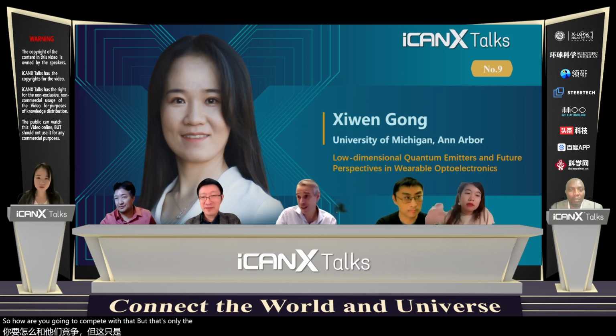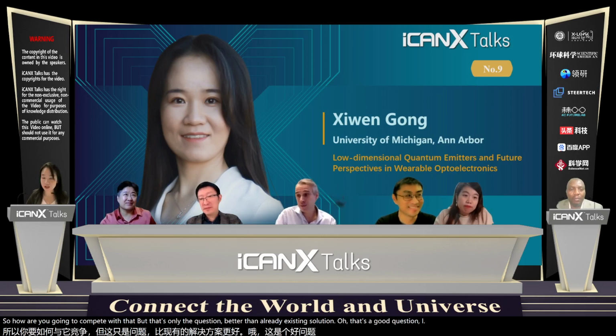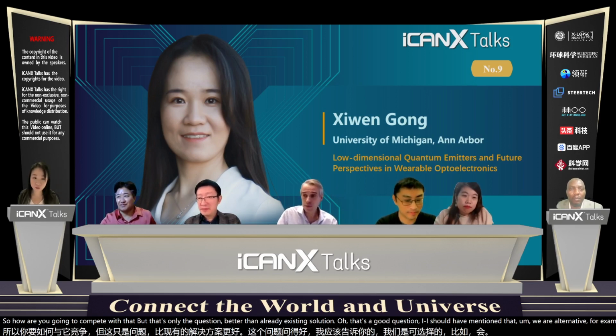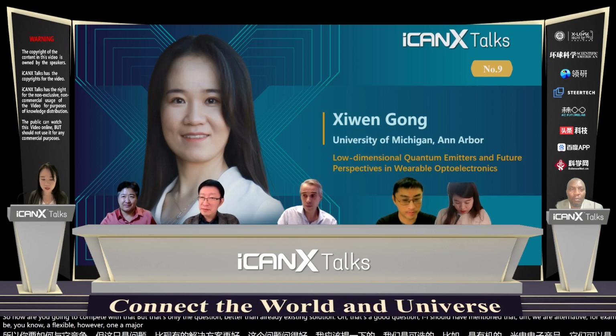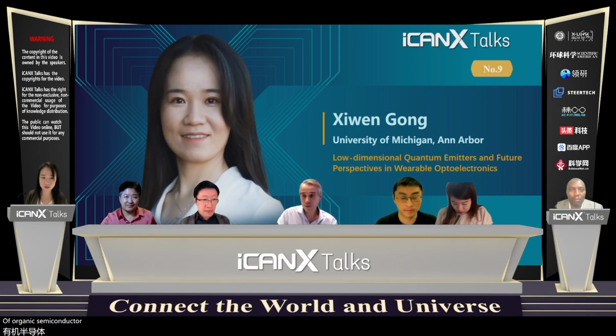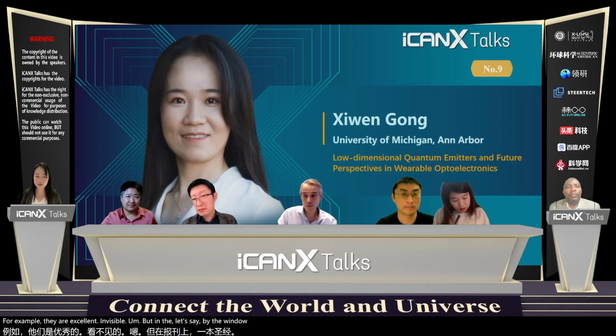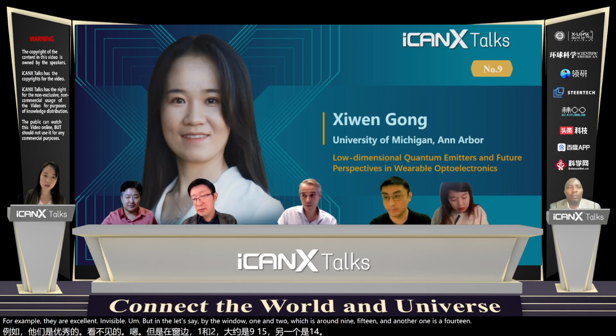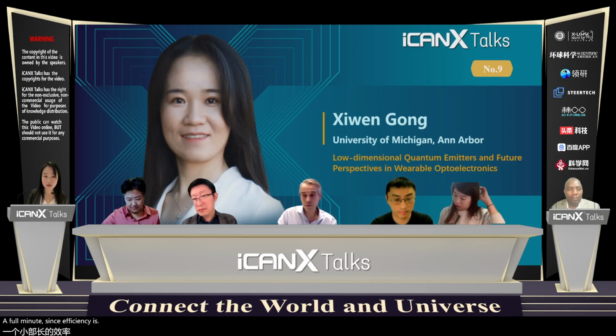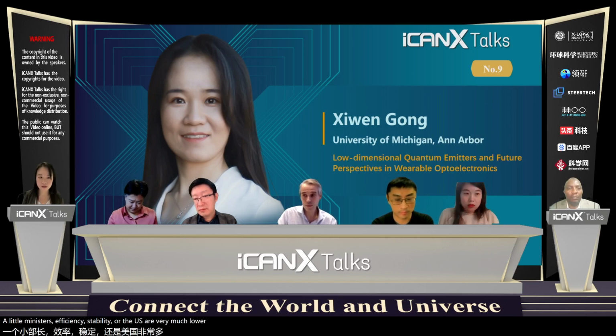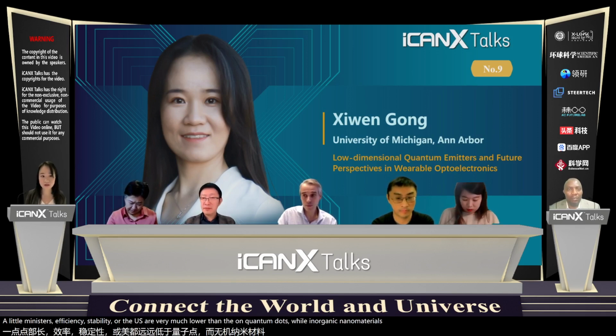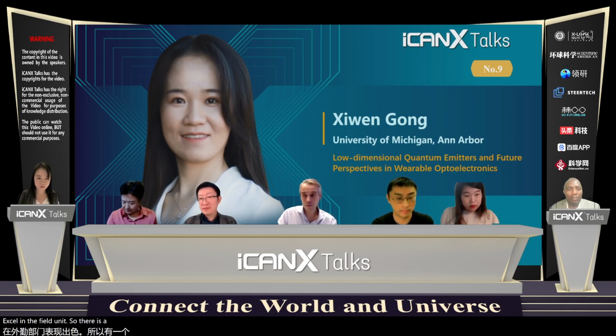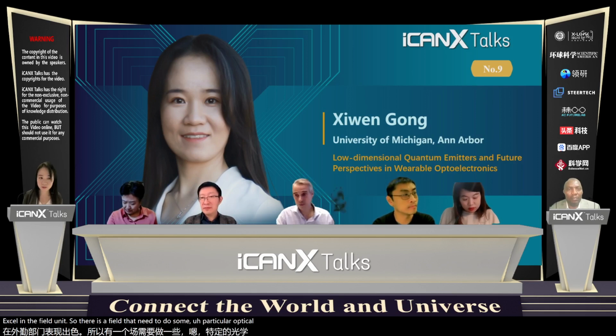Well, that's an amazing question. Be better than already existing solutions? Oh, that's a good question. I should have mentioned that the alternative, for example, would be organic optoelectronics, which could be flexible. However, one major limitation of organic semiconductors is that their response in the near-infrared region is rather poor. For example, they are excellent in the visible, but in the, let's say, bio windows 1 and 2, which are around 950 and 1400 nanometers, their photoluminescence efficiency and stability are very much lower than the quantum dots, while inorganic nanomaterials excel in this field uniquely. So there is a field that needs these particular optical properties that the alternative could not provide.